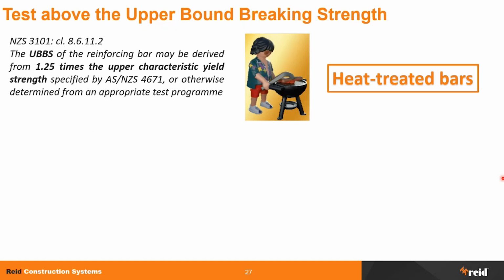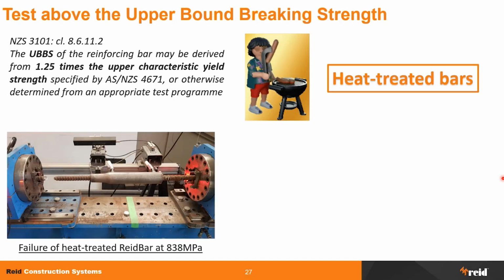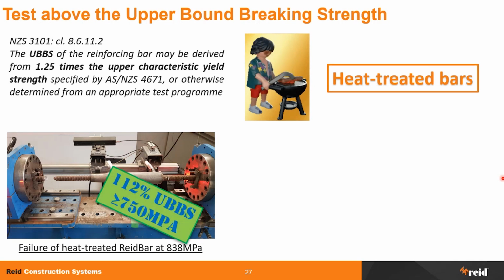This allows us to bring the bar to an ultimate strength that can be anywhere between 800 megapascal and 1100 megapascal. It's not very consistent, but it's consistently above the threshold of the 750. So it does the job. And just to give you an example, just some random results that we had. In this case, for example, we still didn't manage to break the fitting. So the idea with this test is to try to break the grout sleeve or to pull out the bar, not to break the bar, but it still happens. In this case, for example, it was at 838 megapascal of stress on the bar, which is 112% of the upper bound breaking strength, so all good.